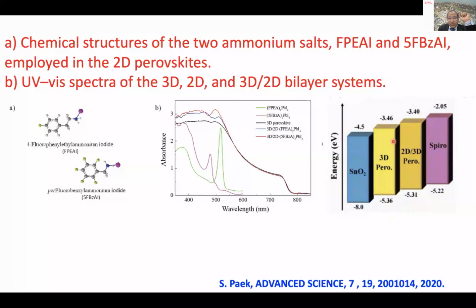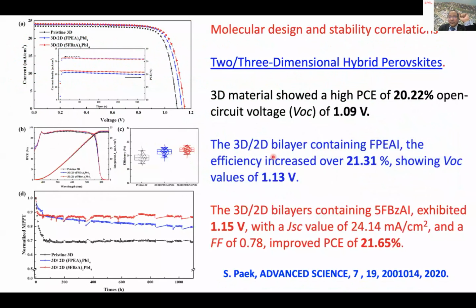By doing that, you can see the photovoltaic data. So the reference sample gives you 1.09, that's voltage. By using one of the two-dimensional perovskites, it increases to 1.13, and the second one, pentafluoro cation, enhances it further to 1.15. It's not only increasing this VOC, which is an indication of the reduced recombination, but it enhances the stability significantly, over 1,000 hours measured.